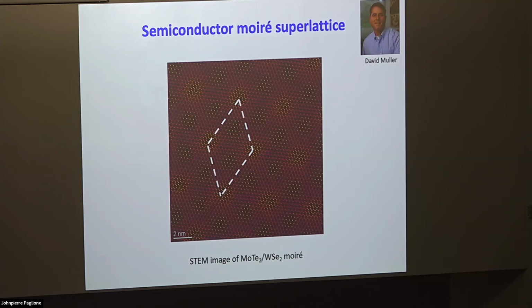Right. So I guess the analogy would be you had two atoms and you have double the bands or whatever. You can also sometimes even have these three different sites, an additional local minimum for that. Then you can also think of it as having two atomic sites, and it becomes something that's called a charge transfer insulator. When you put the first electron, it will go to this site, and the second electron will go to that site because of Coulomb repulsion. So that's a charge transfer type of picture. So it has some analogy also with a local picture of chemistry as well. Thank you.